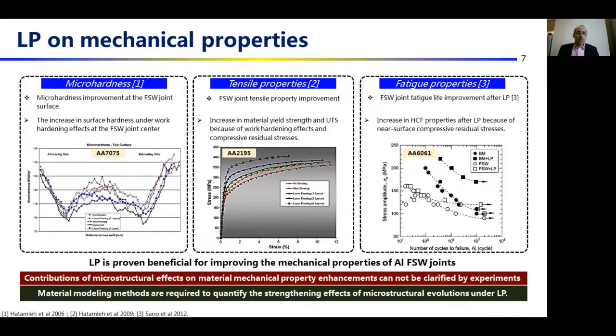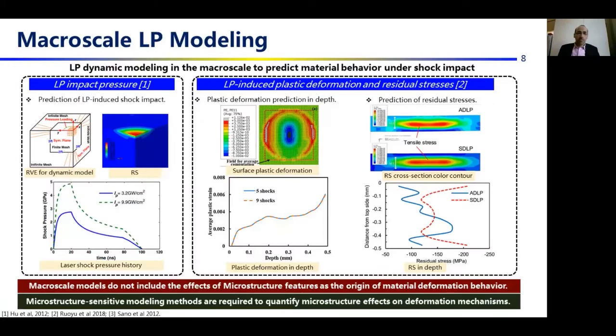However, the contribution of microstructural effect on material mechanical property enhancement cannot be clarified by the experiment. For this purpose, material modeling methods are required to quantify the strengthening contributions of microstructural evolution under laser peening. Dynamic modeling of laser peening in the macro scale has been developed to predict the laser shock pressure history as well as the material plastic deformation under laser peening and the resulting residual stresses in the material after laser peening.